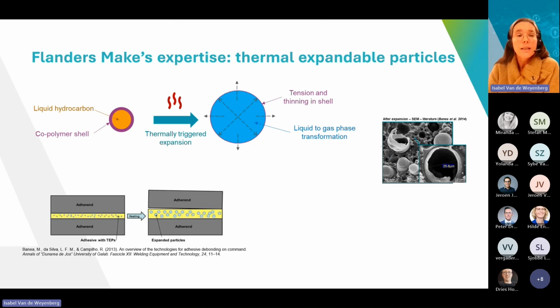Another technology is the technology of the thermal expandable particles. These particles contain liquid hydrocarbon. At a certain temperature, this liquid will change into gas and the particle will really expand. And that's something that you see here on these photographs as well. If you mix these particles in your adhesive, you see what's happening. Your adhesive will start to swell and your adhesive will pull apart or push apart your adherents and they will come loose.